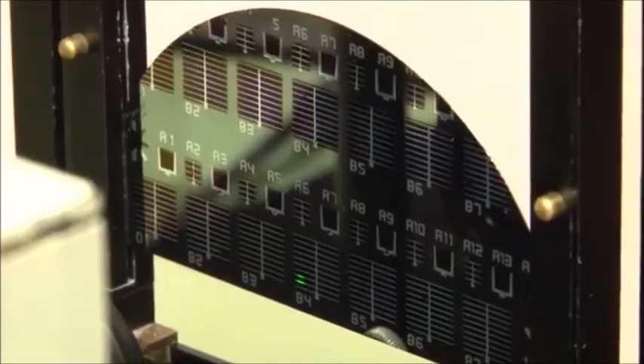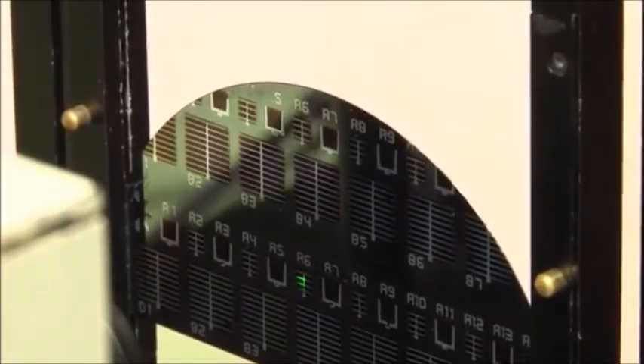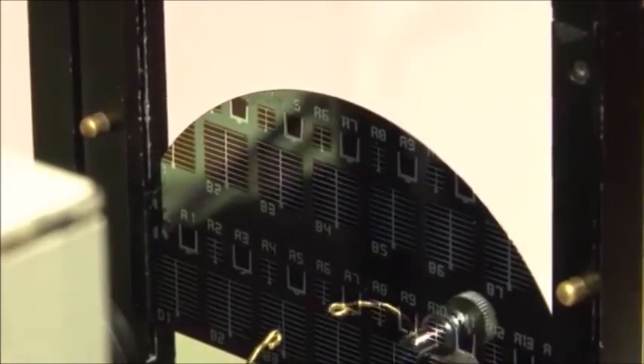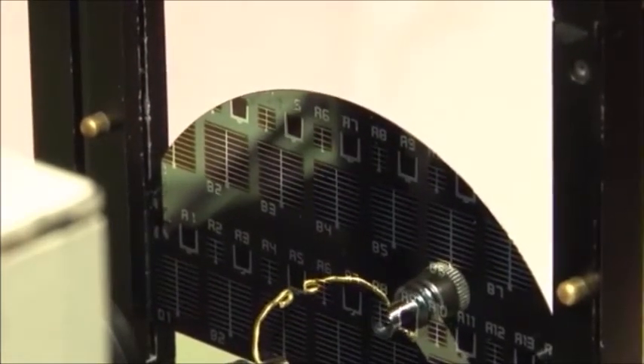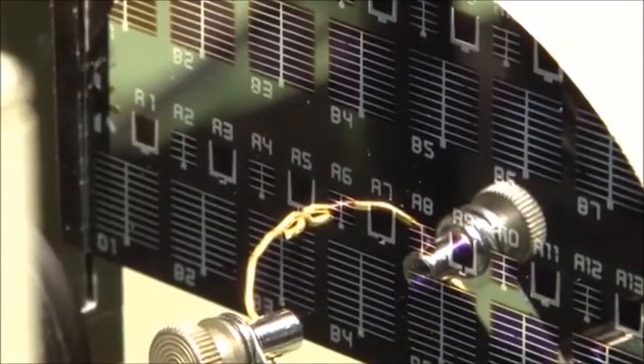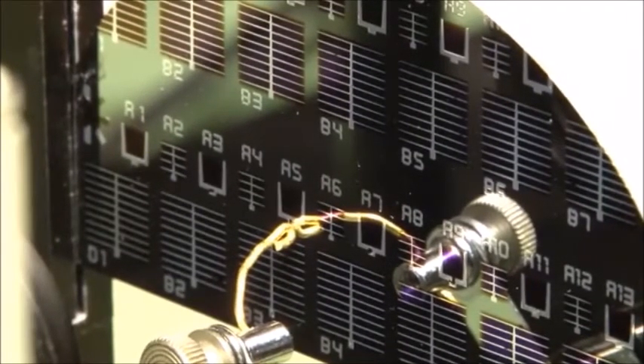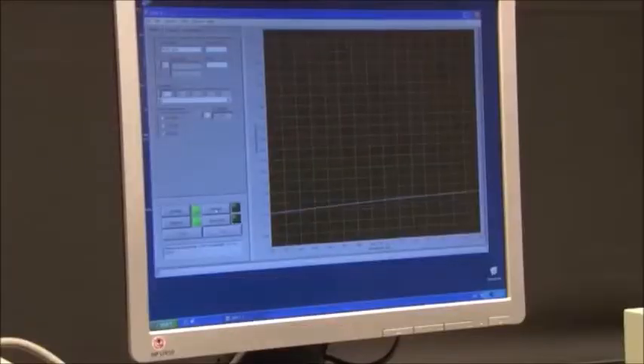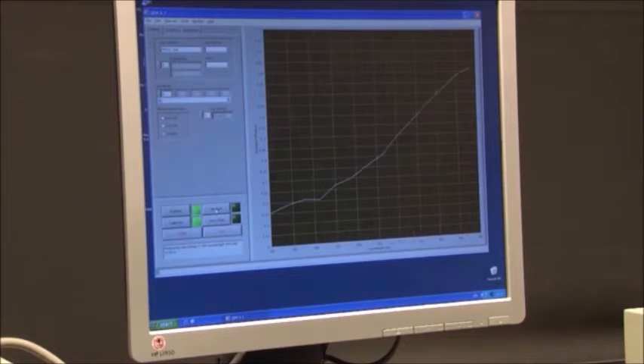The solar cell is positioned at the same spot as the calibration photodiode. The contacts are connected to the ampere meter to measure the generated current. In this example, we measure the cell under short circuit condition. It means that no additional voltage bias is applied to the solar cell. The external quantum efficiency is measured as a function of the wavelength, and in this movie it is going from the blue to the red. The EQE can also be measured when additional reverse or forward bias is applied to the solar cell.